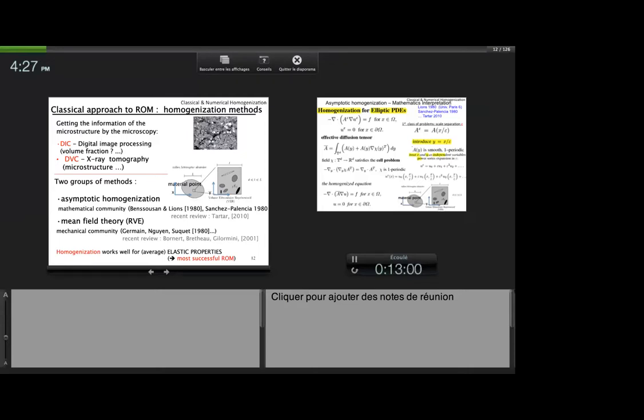In Cachan, we had a group working on that who are quite successful and really known, at least in France. Then you cannot get only surface measurements. For some things, you need 3D measurements. So you have digital volume correlation. In other words, you get X-ray measurements on tomography. The only curse, you cannot do it on a very large specimen. And you can get the fine scale, what really happens in the microstructure of the material.